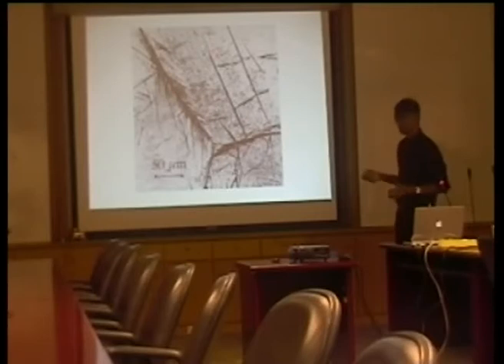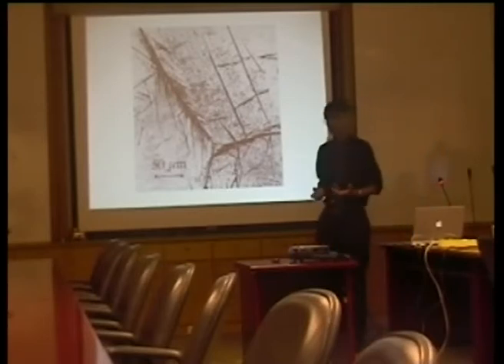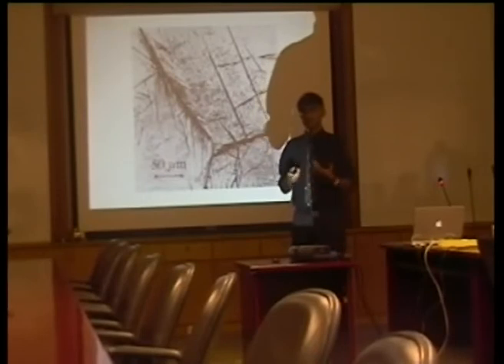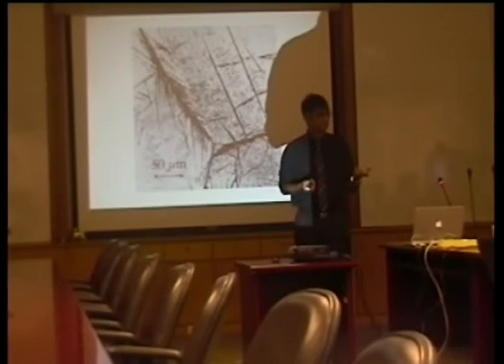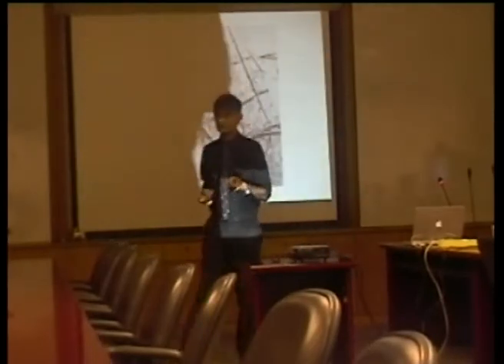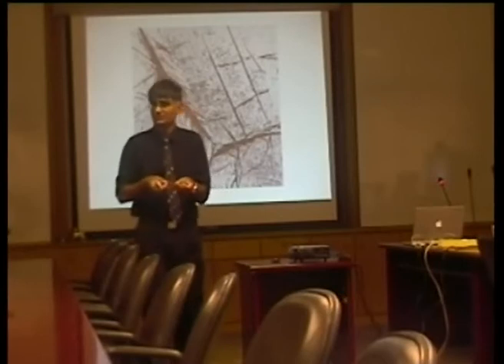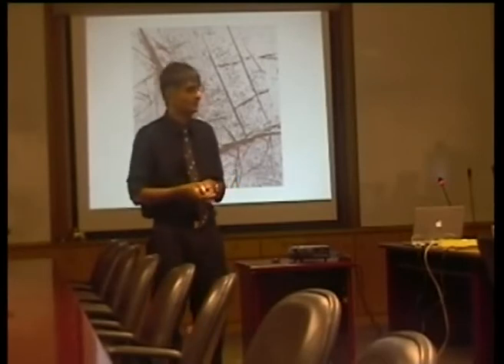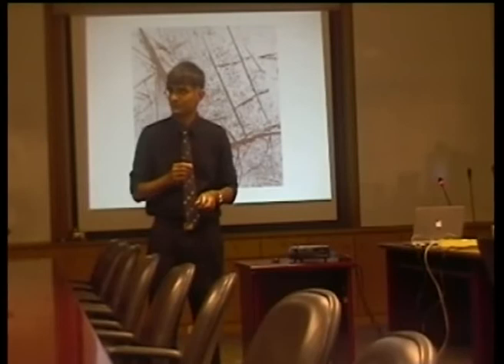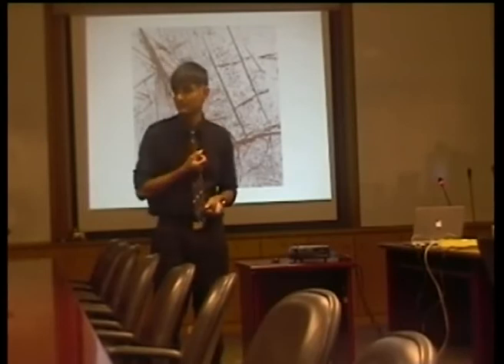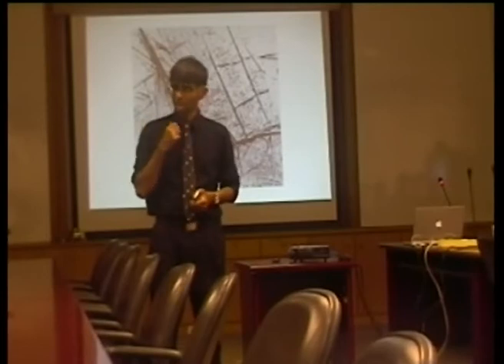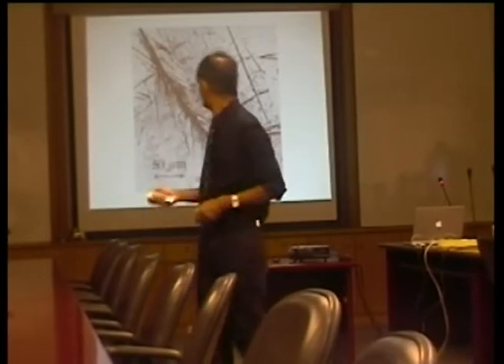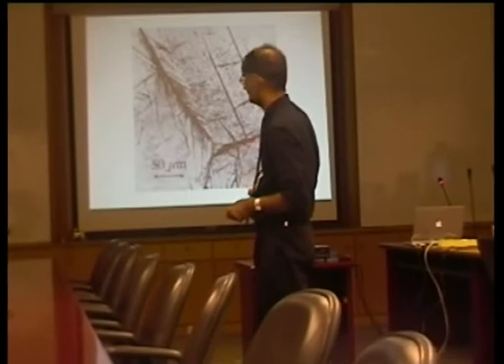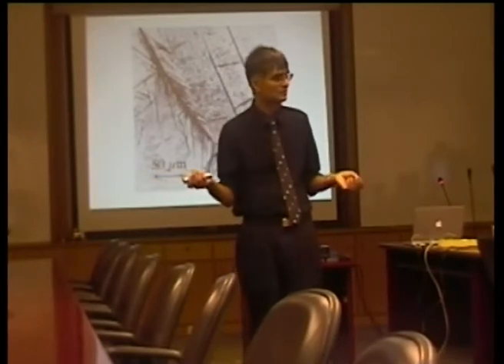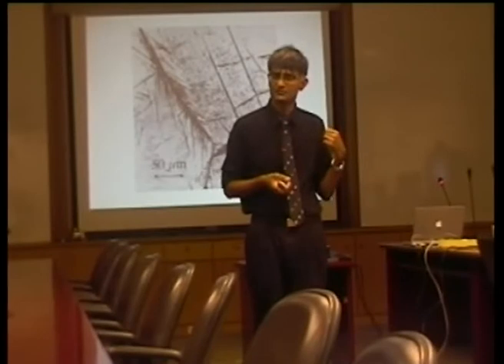Why does this etch black? Why, when you etch a sample, do you get a dark color? You get a dark color because there is a lot of detail inside that feature which scatters light so that the light doesn't go back into your eyepiece. So what this optical micrograph shows is that although this appears to be a homogeneous single plate, there's actually much more detail inside there. Okay.